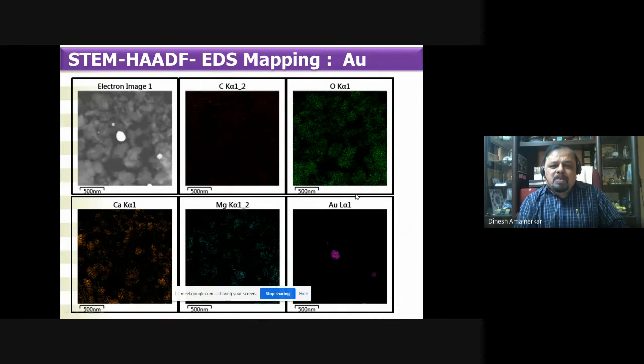Okay. Now you can see that there's some kind of carbon, obviously expected in this kind of biogenic synthesis involving the use of plants, herbs, shrubs, and biological materials. And you can see here oxygen is everywhere. Calcium is everywhere, and magnesium is also here. But much more is calcium and oxygen, as if it is calcium oxide. And here it is gold. We can clearly confirm this in the elemental mapping. So we said that X-ray diffraction is very clean, just metallic gold. But this image indicates the presence of a kind of oxide, calcium oxygen, magnesium oxygen, in what form we don't know.